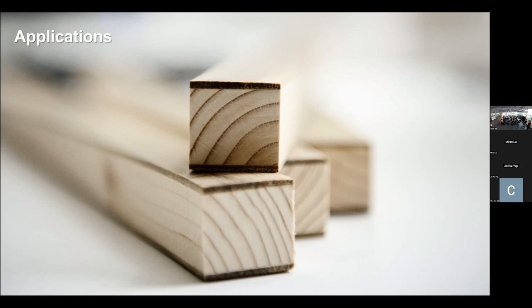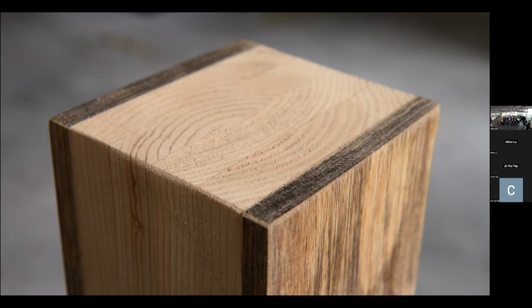So like that, we don't need a huge amount of LVL. We need very thin layers. So in terms of life cycle assessment and carbon emissions, and considering the transport, we would still manage to compete with even steel and concrete. And also when we started to look into the strengths, we would be able to improve the mechanical capacity of the beam, even with the timber, by almost 20%. So we would have achieved more strength. Also, we would have achieved more sustainability compared to steel and concrete.